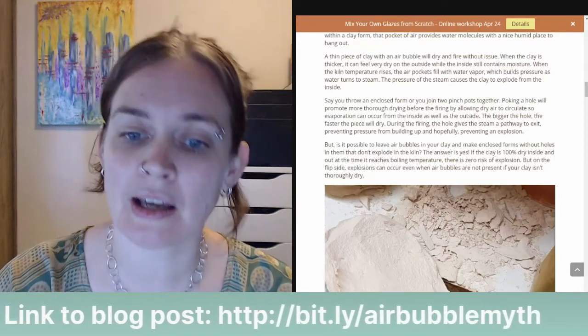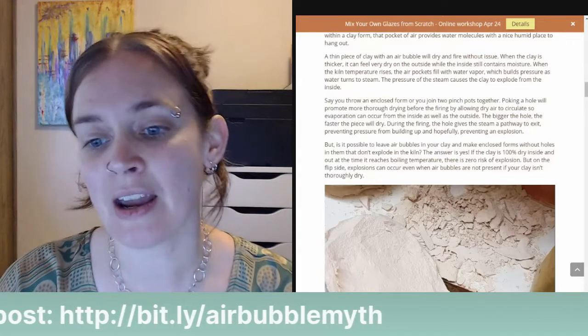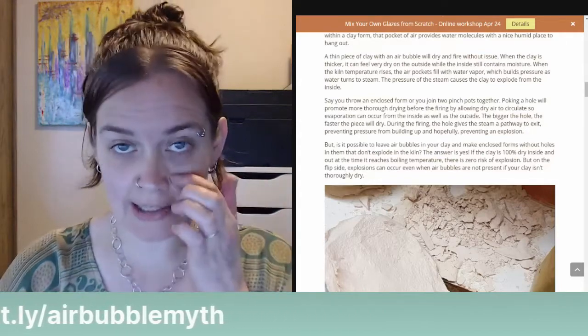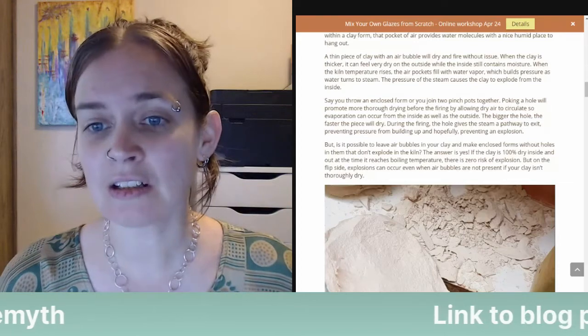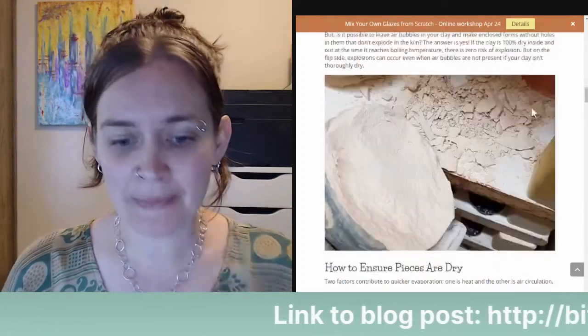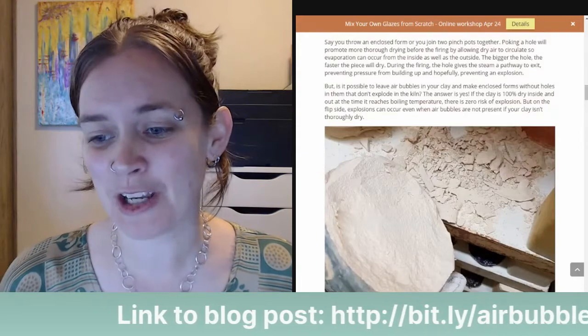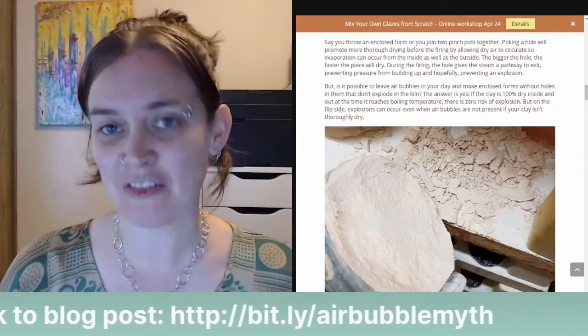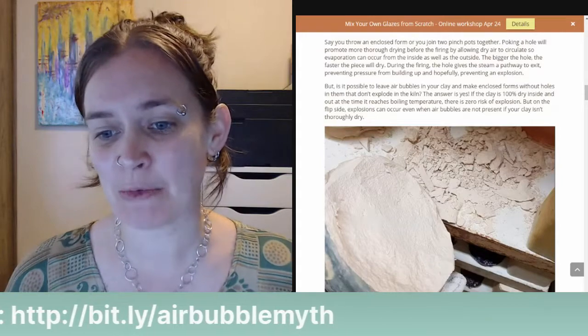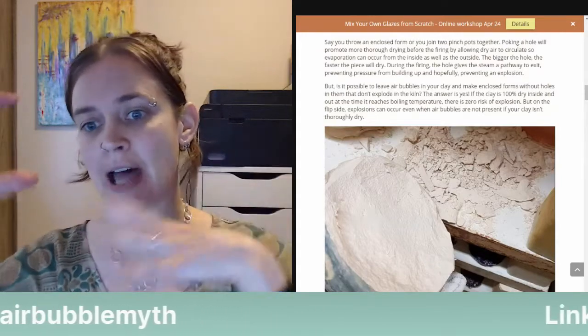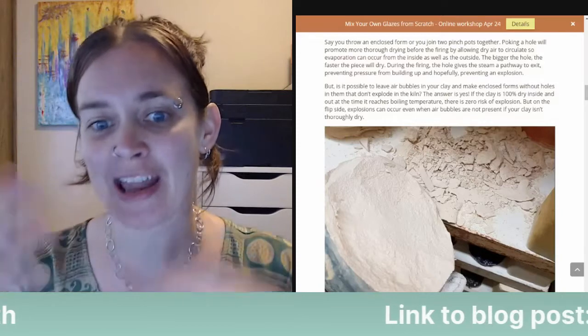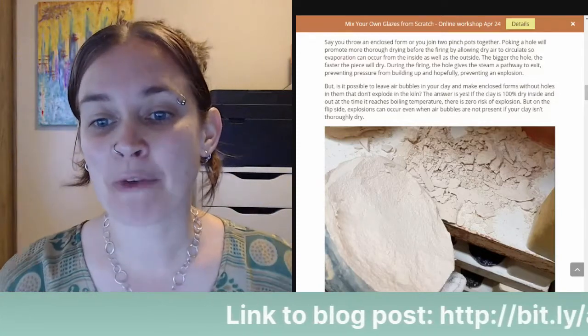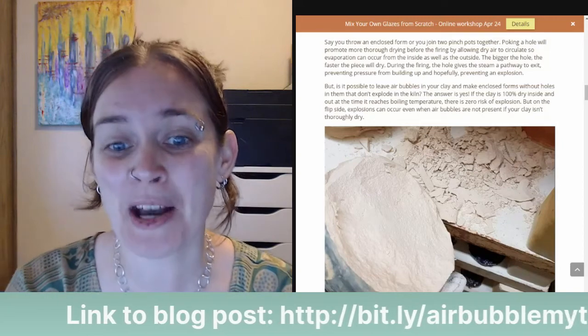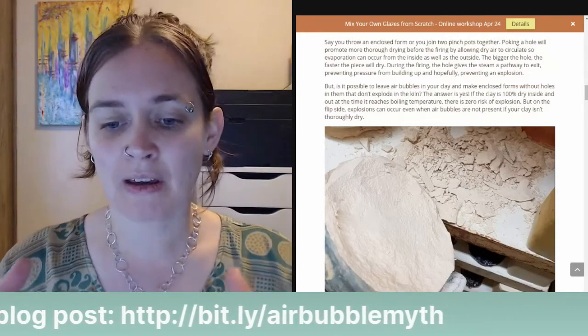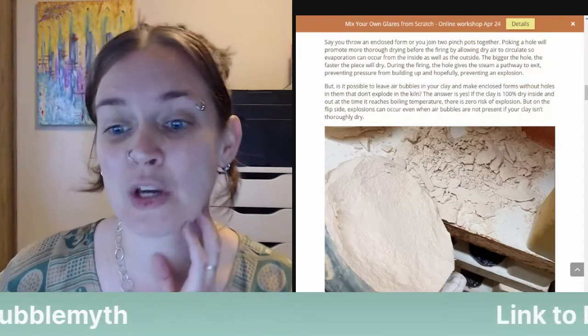But on the flip side, explosions can occur even when air bubbles are not present if your clay isn't thoroughly dry. So here's a lovely example, this was at Cedar Hill Studio where I work. This was a child's piece of pottery, which this often happens with. They often make these really large, elaborate forms that take forever to dry, and they're super heavy. And we do leave them to dry as long as possible, but sometimes the clay is so thick that the piece feels dry on the outside, but there's still trapped moisture on the inside.